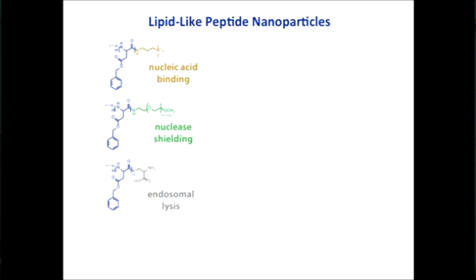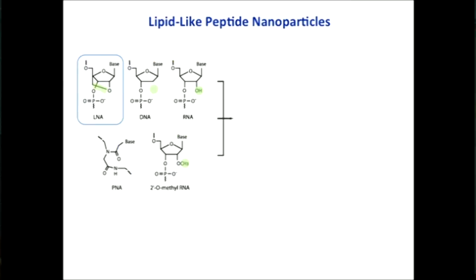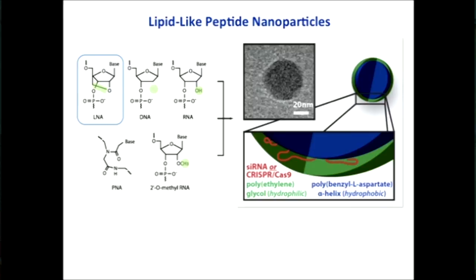We also mix that with systems which have the polyethylene glycol system that allows us to get through the bloodstream. It also prevents breakdown of the RNA. And finally, we have something. This is a zwitterion. It's an acid attached to an amine. Essentially, this amino acid is going to allow us endosomal buffering, and that buffering is going to allow us to escape the endosome. All right, so when we combine these systems together with RNA, in our case, we're using a protected kind of RNA,